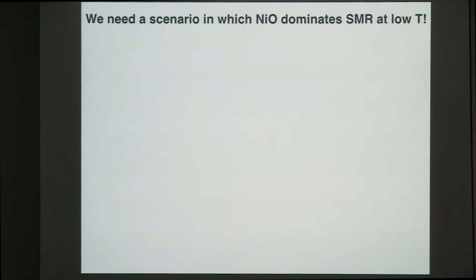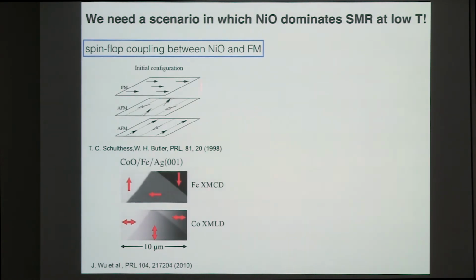So now is our explanation for it. Of course, Felix told you yesterday. We assume this spin flop configuration. This configuration is very well understood. When you put an antiferromagnet on your ferromagnet, a very naive imagination is that it will align collinearly. But you will find that it is somehow not correct, because for the antiferromagnet, if you align them collinearly, the energy will be zero, because you force it to couple parallel and antiparallel. A good compromise is that if the antiferromagnet Néel vector can be coupled perpendicular to the ferromagnet, you can have this finite coupling and further minimize the energy. This can be seen in a lot of systems so far.